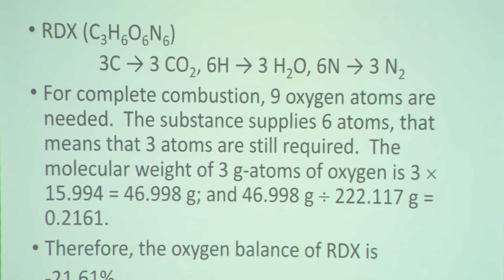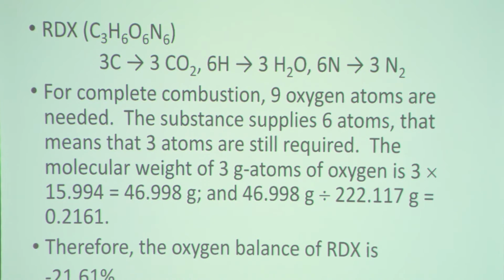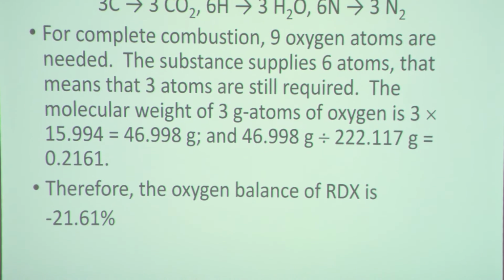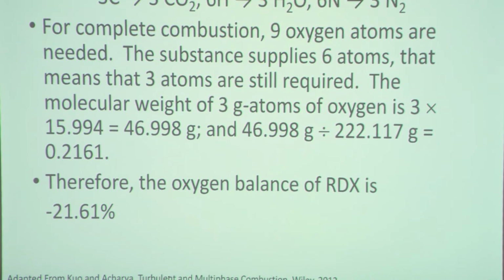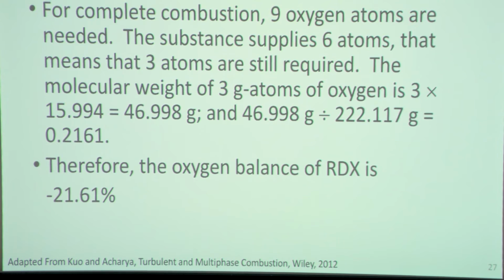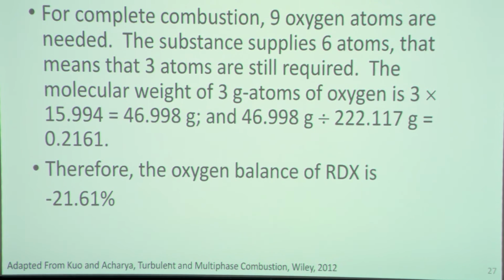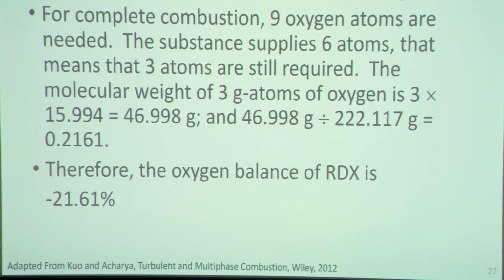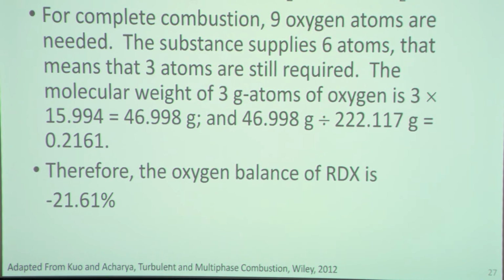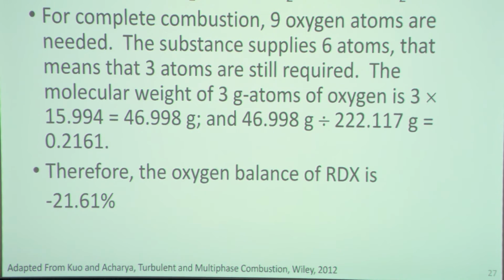If I look at the molecular weight of the 3 oxygen atoms, which is 3 times 16, I get about 48 grams. And if I look at the total molecular weight of the RDX and take that ratio, I'll find that ratio ends up to be about 22%. Okay, but it's negative because I need to supply additional oxygen to complete all the elements to full oxidation. So the RDX would have a negative oxygen balance of 21%. So you might ask yourself, and I'll come back to this, why does one add RDX to a propellant? Since it's not going to supply oxygen, and it's typically referred to as an oxidizer if that's done, but it doesn't supply oxygen to the mixture.